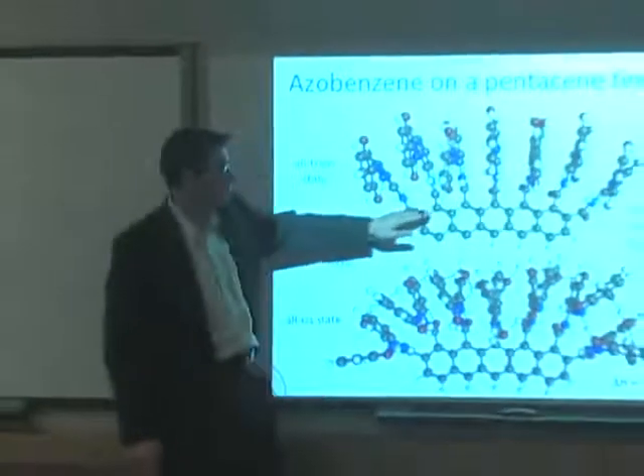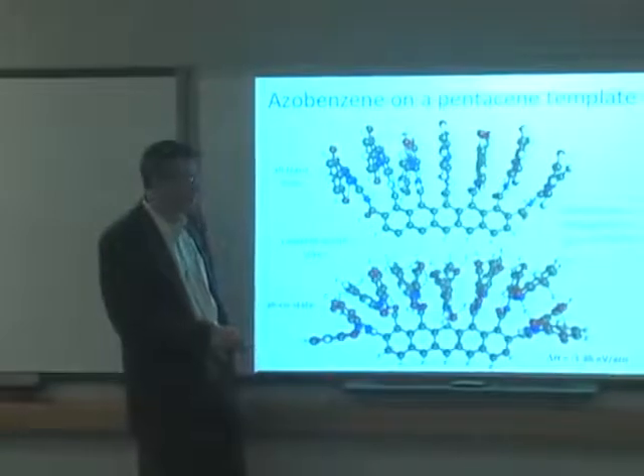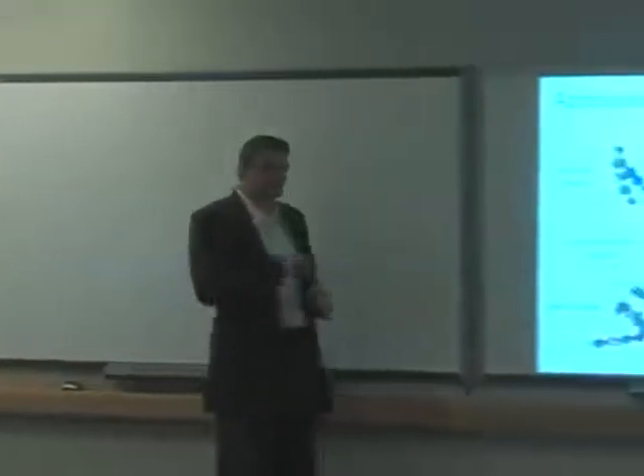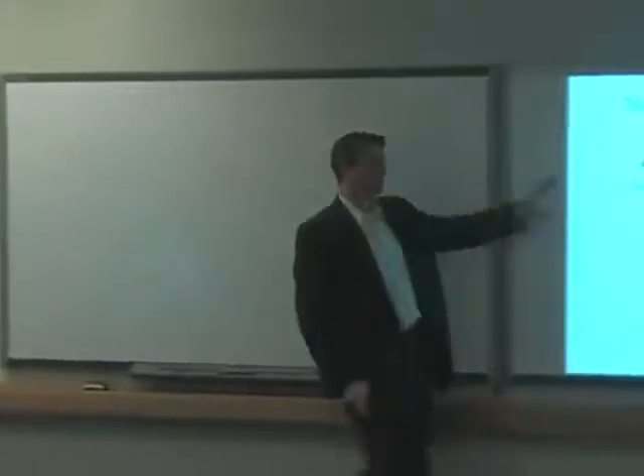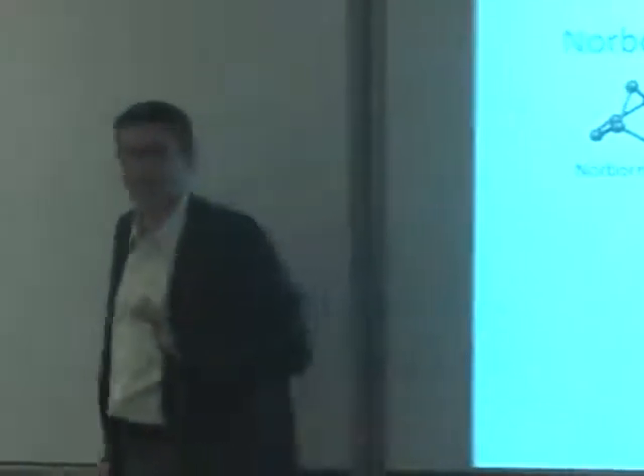And pentacene is an interesting one. Pentacene is interesting because you can make a really strong bond to the outside edge of pentacene. You can get a really nice density per molecule, 1.5 eV. That's about what we got for the nanotube. But it's interesting because of what we found happens for our old friend norbornadiene. If we go back to this one, remember, this is basically the champion of the 70s. The problem with this was that it degrades. Well, we know what those degradation pathways are, and so we can try to play the same trick. And pentacene turns out to be a really nice template for norbornadiene.